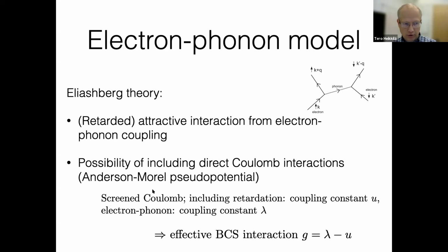Basically, one thing is that you need to take into account the screened Coulomb interaction here, including retardation effects. Such a screened Coulomb interaction is described by effectively a coupling constant U, which is a repulsive interaction. And then the electron-phonon coupling is described by a coupling constant lambda. Once you put these together, the effective BCS interaction will depend on the difference of lambda and U. And if G is now positive, then you get the superconducting state. That's the hand-waving way to quickly go through this, but doing the first line here involves a bit of work. The bottom line is that the screening itself can be a sample-dependent thing, not only a materials-dependent thing, and therefore superconductivity in this sense might not be materials dependent, but actually sample dependent, especially in 2D cases.